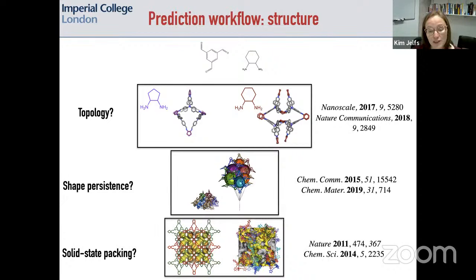And then finally, if you did know the molecular structure, you also have the opportunity to do solid state packing, obviously quite key to knowing how its properties are going to be in the solid state. So we use crystal structure prediction techniques, in particular in collaboration with Graham Day at the University of Southampton in the UK. These are techniques they often use on pharmaceutical organic molecules for polymorph prediction, and we apply them here to predict the low energy structures and therefore the void network of these systems.